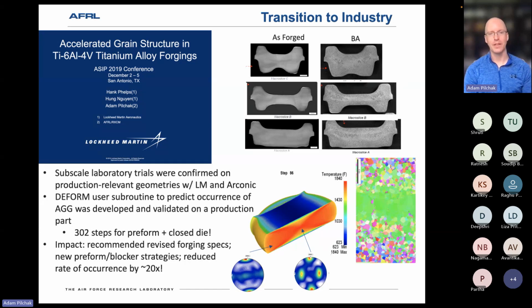And then we created a DEFORM simulation of that entire thing, including the closed die forging step, and attempted to validate that DEFORM user subroutine on that actual part, which was pretty neat. I'd say overall, nominally successful. I don't have any of the graphs from that one, unfortunately, but this is what we saw on the early ones as well. You would see it right in the location my mouse is on, on both sides. It would persist for a while, but this was about a 3-foot-long forging. As you got far enough down the forging, just like we saw in the side pressing, the abnormal grains would shut off, and we were able to predict that relatively closely.